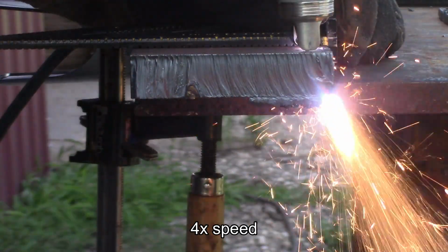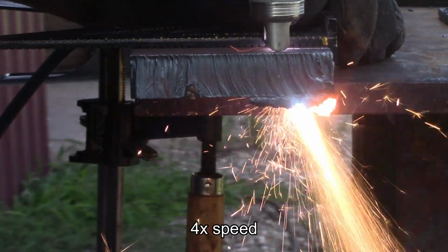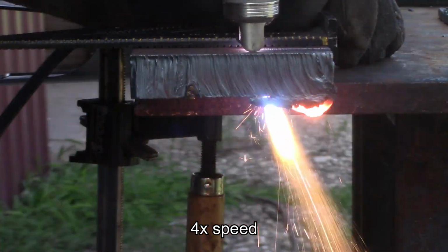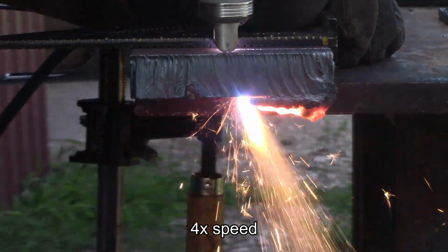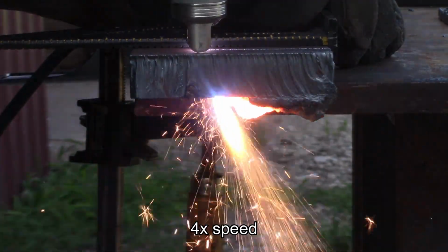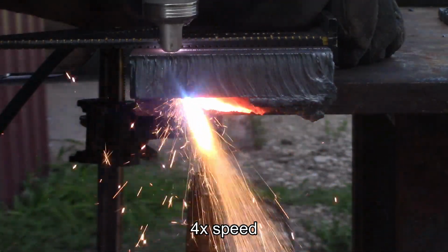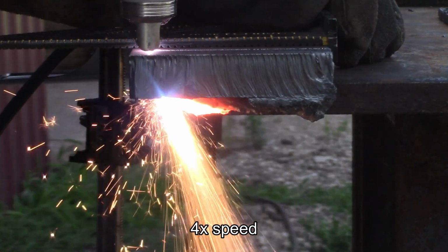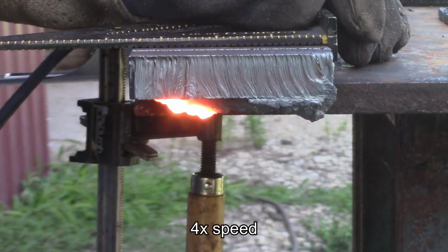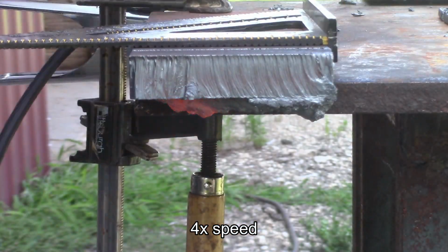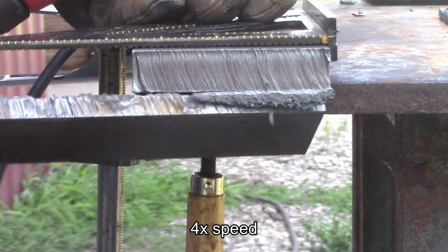Next, I decided to push the limits and cut some 3/4 inch or 19 millimeter thick stock, which is well outside the range of the plasma cutter, but it handled it quite well. I was maxed out on amperage and pressure and had to slow way down on my feed rate, but it still cut through pretty easily and produced a surprisingly clean cut.